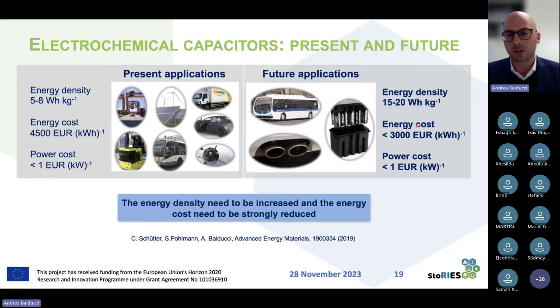So from the 5 to 8 actual watt-hour per kilo, we should try to move to 15, 20. So basically, we have to double the energy density of this system. At the same time, we should keep the cost of the power as low as it is now, but we should reduce significantly the cost of the energy.